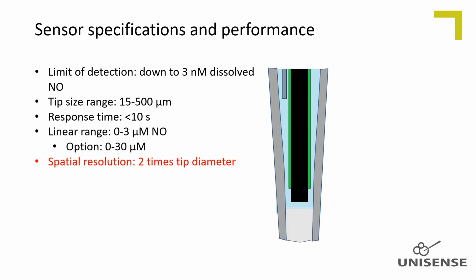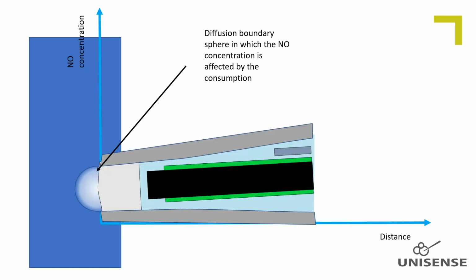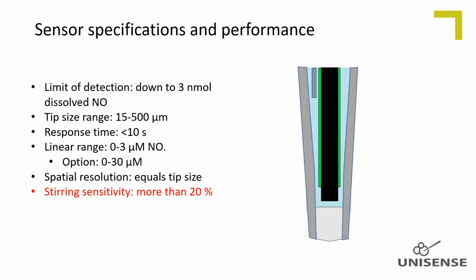The estimated spatial resolution of nitric oxide sensors is 2 times the tip diameter. This is just a rule of thumb because it cannot easily be validated. Compared to other Unisense amperometric sensors, the large consumption rate will to a higher extent deplete the analyte at the membrane/sample interface. So compared to other Unisense microsensors with a very small analyte consumption rate, the sensor will sample nitric oxide from a larger diffusion sphere at the membrane/sample interface, in which the natural concentration will be affected by the sensor consumption. So the sensitivity to stirring is for standard nitric oxide sensors more than 20%.